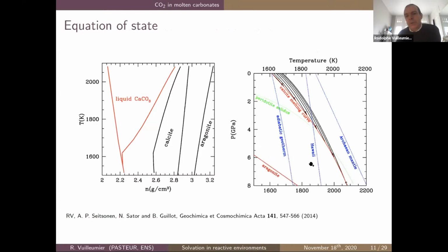And here's an example of a geological application where we could look at the melting curve of calcite. A bunch of material will go up in the Earth's mantle, and at some point the calcite will melt, and if the mantle is hot enough, then it can reach the surface. What we can see is that with the current adiabatic geotherm, seldom will carbonates reach the surface, except in some hotspot. This is the one in Hawaii, but Tanzania is one hotspot of the same kind.